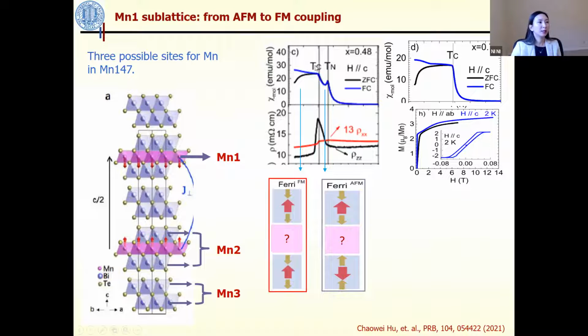And then once you enter into this ferromagnetic state, you start to have this so-called ferrimagnetic phase, which means your manganese 1 sublattice will be parallel to each other, manganese 2 will be ferromagnetic. However, the coupling between these 2 sublattices is going to be antiferromagnetic. So we believe that's what happened here, right? But then the next question is, yes, it's all natural, based on the knowledge of manganese bismuth 2 tellurium 4, come down to the understanding or the hypothesis of the magnetic structure of the manganese 1 and manganese 2 in this doped 147.